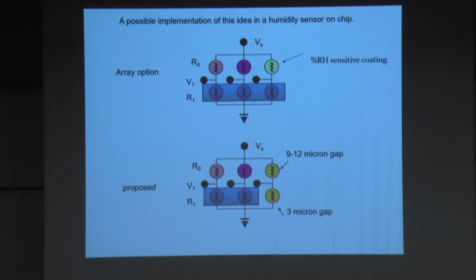The normal humidity sensors is in the upper picture. It's an array where you have 3 different coatings, and you get some kind of fingerprint effect. And if one of them is sensitive only to RH, you can monitor your relative humidity very easily. The one that I'm suggesting, according to this work, is actually to leave this one uncovered, but make it with different electrodes, one with a 3 micron gap and one with a 9 micron gap. When this sensor will encounter a solvent, both of them will respond in the same way because there is no gap effect. However, if they will encounter relative humidity at high humidity, this will respond.